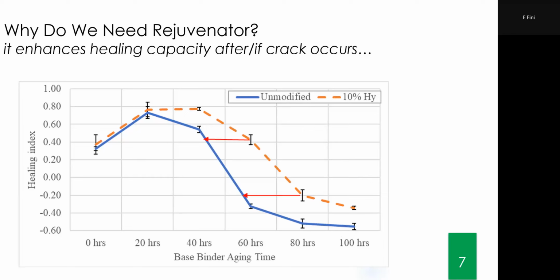In this scenario, we applied the rejuvenator, and you can see that at every point in time we improved healing a bit. For instance, at 80 hours it shifted to almost the same as 60, and 60 was almost the same as 40. So we recovered 20 hours' worth of aging. It's sort of like if I could make you 10 years younger. This could make the material a bit younger. It could not make it go back all the way to zero, but it was able to make it a bit younger. So the healing capacity was recovered to some extent.